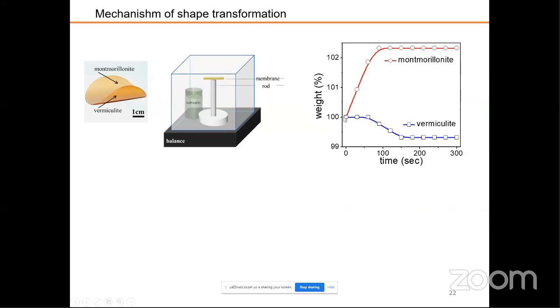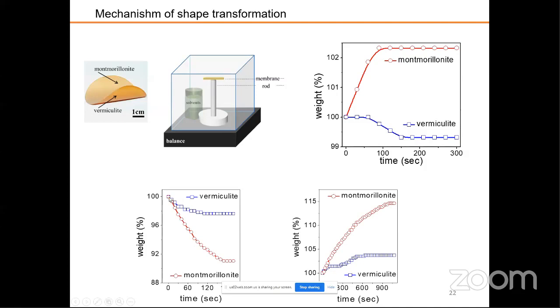So what we found is that vermiculite does not take up the methanol or atmospheric molecules when exposed. On the other hand, montmorillonite takes up the atmospheric water molecules or solvent molecules and increases its weight, while vermiculite remains constant. Similarly, in a highly humid area also, vermiculite weight does not change much. On the other hand, the montmorillonite case is very much affected by the atmosphere. That we have already shown in the first slide. In this case, montmorillonite has less charge on its surface, so it can easily take up molecules or get expanded.